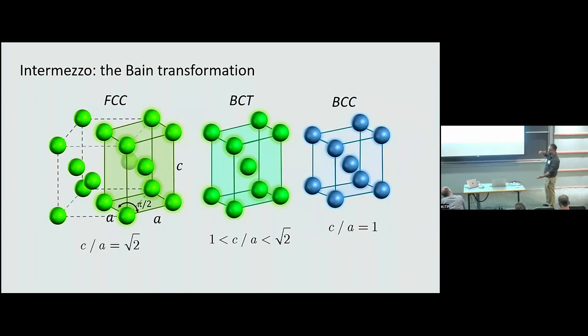And if you start compressing this cell, when you get to C over A equal 1, then that's BCC, and everything in between is BCT. This is known as the Bain transformation. So there is a continuous structural transformation between FCC and BCC.